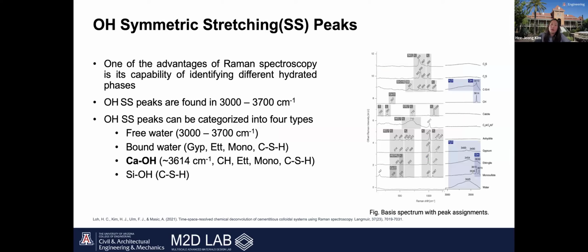So one of the main advantages of Raman spectroscopy is its ability to identify different hydrated phases in cement, such as CSH, gypsum, ettringite, monosulfate, and water. And the OH symmetric stretching peaks appear in the range of 3,000 to 3,700 per centimeter, and they can be categorized into four different types: free water, bound water, CaOH, and SiOH. So in this study, we focused on the OH symmetric stretching peaks, particularly the CaOH-containing phases, to better understand the hydration reaction and the formation of CSH during the early stages of cement hydration.